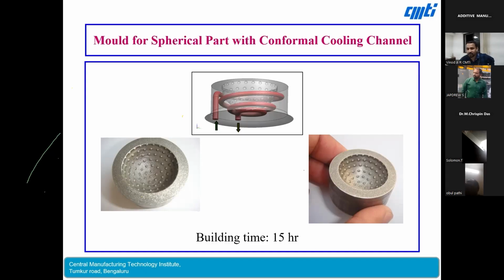But you can see one example. This is a hemispherical or spherical part. If there is a hemispherical surface and you want to make a cooling channel, you cannot make a curved hole like this in a CNC machine, right? So you need to make a straight hole. When you make a straight hole, at some areas the cooling channel will be very close to the surface where you need cooling, and in some areas it will be far off. Wherever it is nearer, the molten polymer will solidify very fast. Wherever it is away, it will take more time. Because of this differential cooling, the cycle time for cooling will be higher, and because of the differential thermal process, defects may also form in the part.